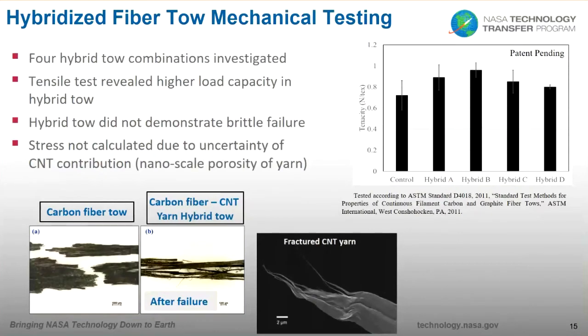So a tow of only carbon fiber was used as the control material, and then we looked at several hybrid tow configurations, all having increasing volume concentrations of carbon nanotube yarns. The tow test showed this really nice trend where the tenacity increased with increasing carbon nanotube yarn concentration up to an optimal value, followed by the tenacity decreasing.